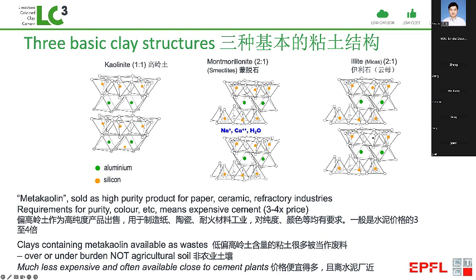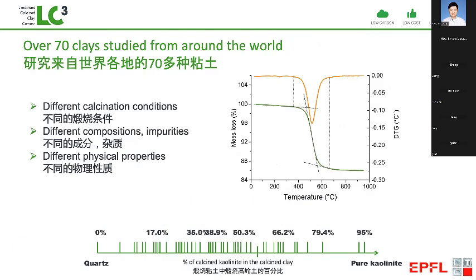Now, we don't need high-level metakaolin. This is very important because when people look at reserves, then they are talking about very high purity materials. We only need around 30 to 40% of this mineral kaolin. And the reserves of these kind of clays are many, many orders of magnitude higher than those for pure metakaolin, maybe 1,000 times or even more. And these are often wastes which are over or underburden, results of tailings from other mining operations, etc., which can be reused. So we have now tested more than 70 clays from around the world.